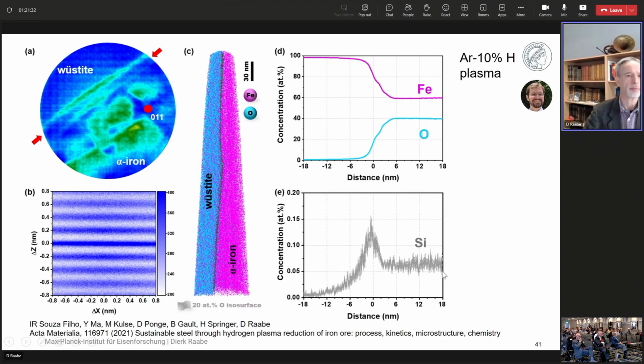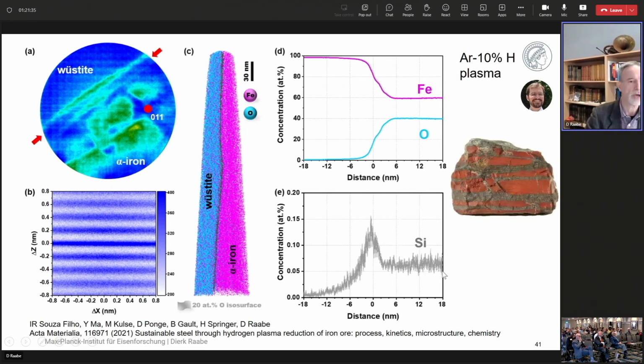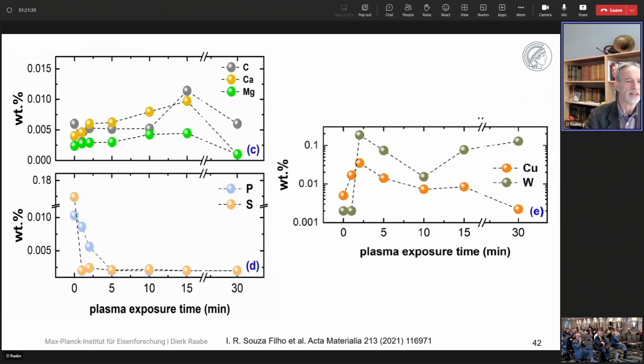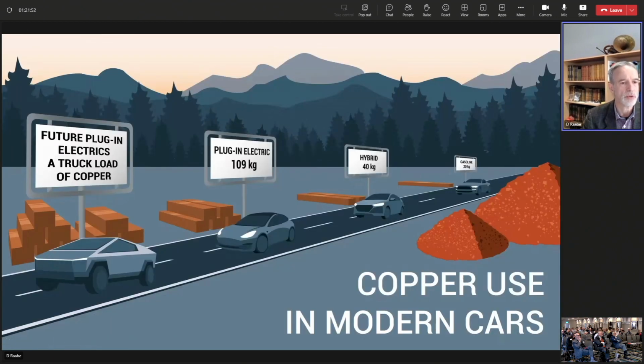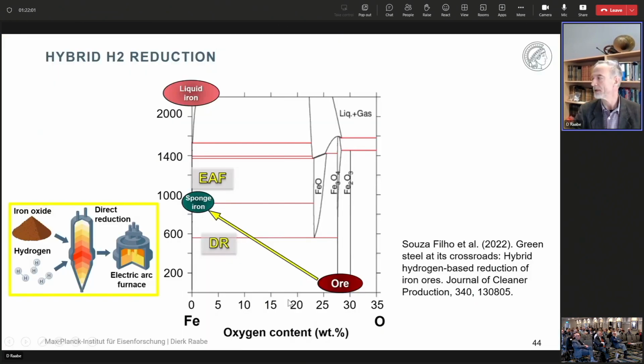And again, that's very important for the future when you want to use low price, for instance, banded silicon-containing iron ores. A second little detail is that you also remove the copper in the plasma. That is a very complicated thermodynamic step, which we have not fully understood yet. Just it's interesting in the electrification that we all know you get massive amounts of copper and tin and zinc into steels that are not so easy to come by. And when as a side product we get this removed, that would be very positive.